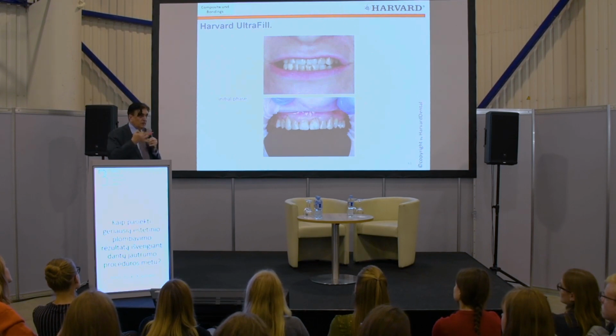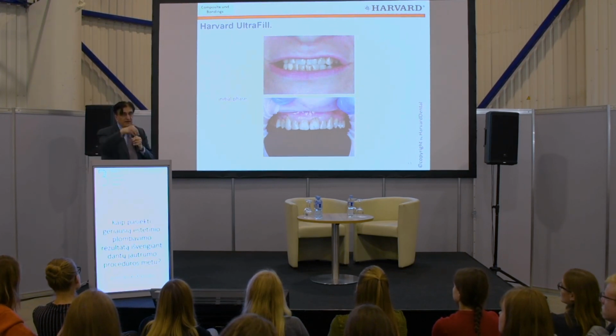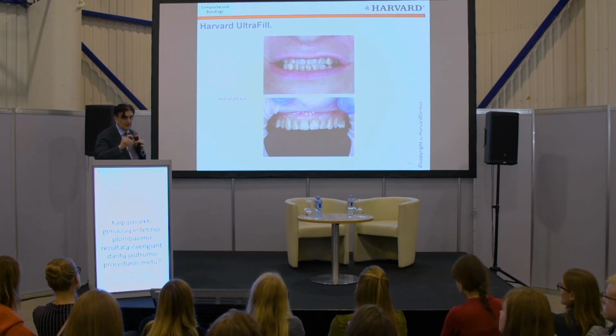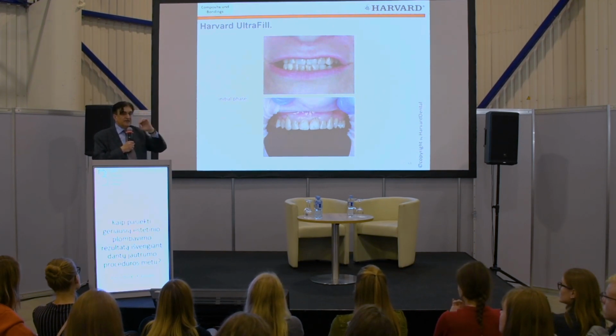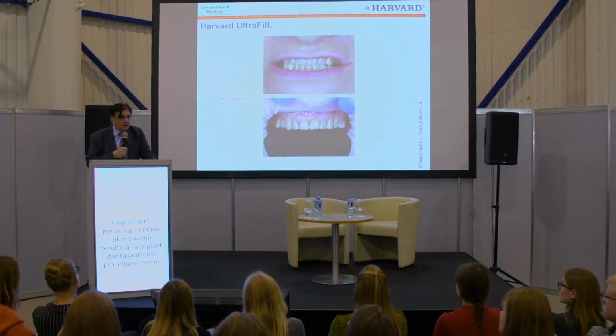So in order to have a very good, long-lasting composite filling, you should understand how the adhesive works. Two things, don't make it complicated. Either you remove the smear layer and demineralize the dentin, or you penetrate the smear layer in order to let the bonding integrate and form a hybrid layer between the dentin and the composite filling. So just remember these 2 things. And most probably the sensitivity you get with composite fillings is coming from you as a dentist. You create more damage than you're helping the patients.